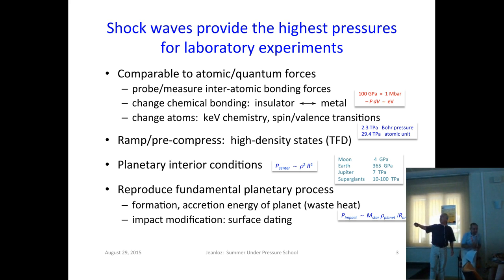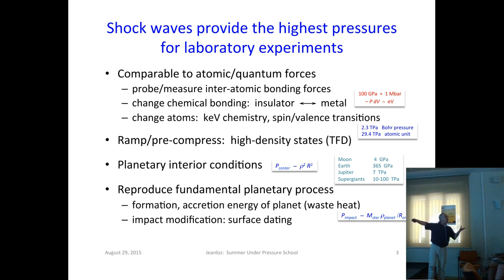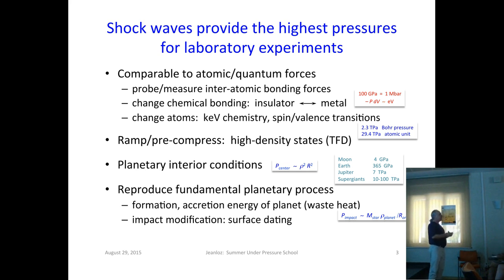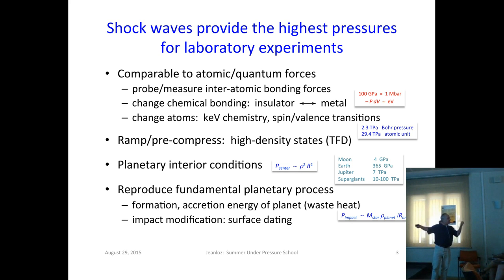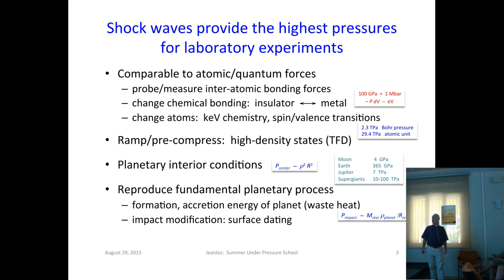In a different context, we've heard that if pressure is of the order of a megabar, the compressional energy — pressure-volume energy — is of the order of electron volts. This is why chemistry fundamentally changes at megabar or 100 GPa pressures. The quantum force that holds the electron from collapsing into the atom has pressures of the unit I'll call the Bohr pressure, of 23 megabars — 2.3 terapascals. That's a fundamental property of the atom, compared with the atomic unit of energy density, which is nearly 300 megabars, 29.4 terapascals.